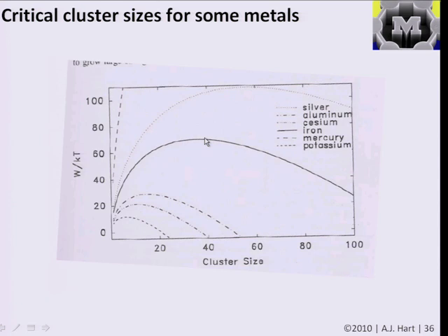conditions. I think this was a case where you had a background pressure of about a half torr, and you had an equilibrium vapor pressure of, say, 0.01 torr. So here, the supersaturation is about 50.